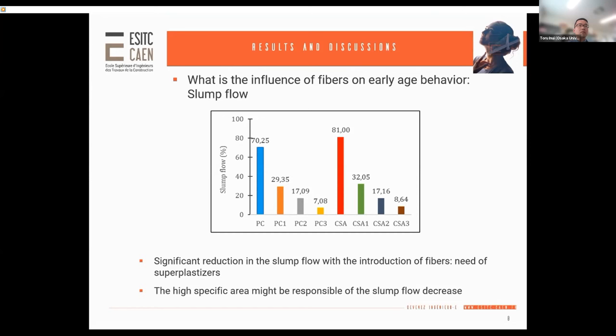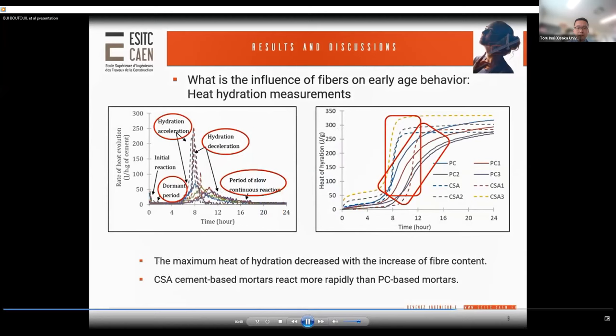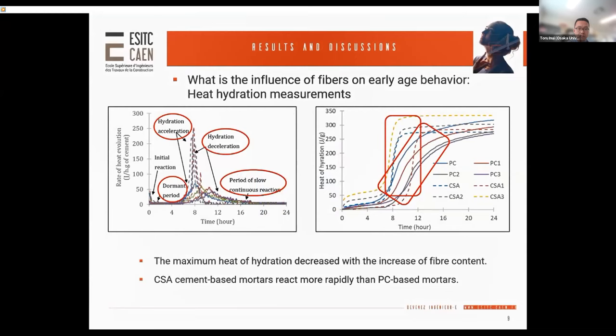So here we are presenting the influence of fibers on the early age behavior, taking into consideration the heat of hydration for the two types of cement. First, regarding this heat of hydration, the four steps during the hydration time of mortars, including the dormant period, the hydration acceleration, the hydration deceleration, and the period of slow continuous reaction, can be identified in accordance with the well-known hydration behavior. The presence of fiber influences the heat of hydration development and behavior differently depending on the cement type and fiber content in mortar, as we can see from this figure.